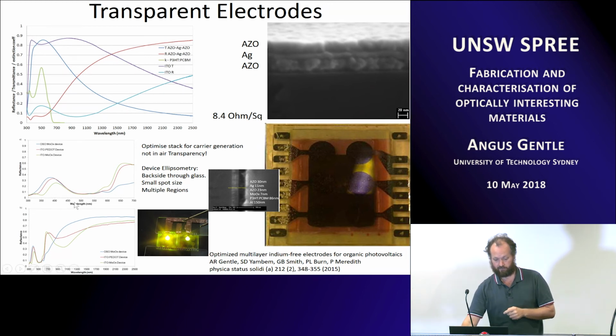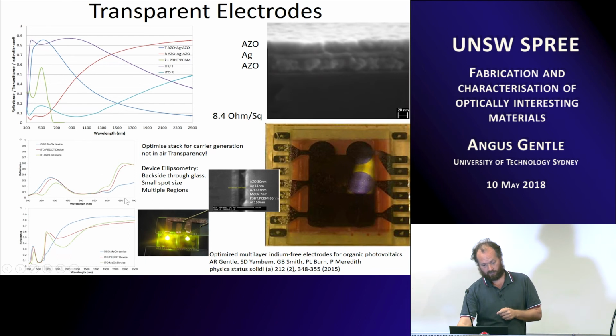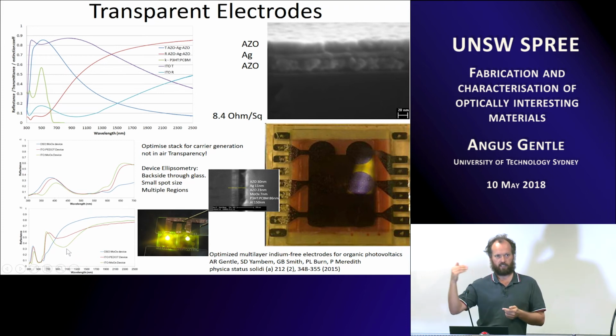And so the other interesting thing here, you can see it's absorbing more light. So it's absorbing out to here. This big dip there is actually with moly oxide, it's not MoO3, it's a suboxide to actually get it to be the right work function. And so that's the big absorption band you see optically from it as well.